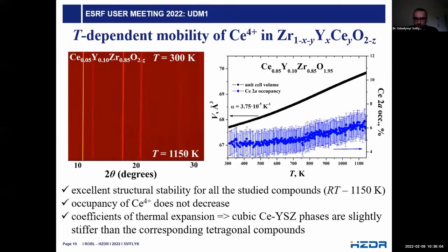And also what is important, the occupancy of cerium, these guest cerium atoms, which are surrogate atoms for tetravalent actinides, doesn't decrease with temperature. So it stays there. You see, these are the blue dots. So the occupancy of cerium ions remains stable within the error range. And from this kind of data we also obtain important physical parameters, which are coefficients of thermal expansion. And we found that cubic cerium-doped yttrium-stabilized zirconia phases are slightly stiffer than the corresponding tetragonal compounds.